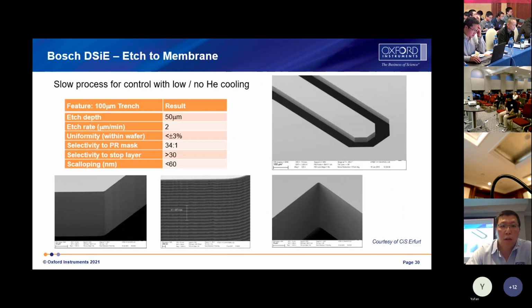A key point to take from this slide is etching from the backside of the membrane. Low etching rate process for control with low or no helium backside cooling. If you use any plasma tool, you know there is a parameter you set for backside helium, and the backside helium helps transfer heat from the sample or wafer to the lower electrode. So adjusting the process maintains a good profile with a clean sidewall, particularly at the corner. Usually you see long striation on the sidewall at the corner.